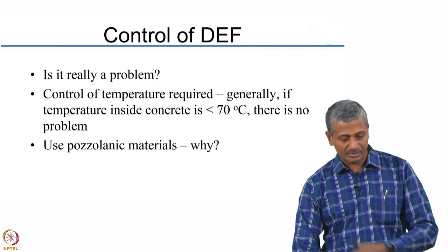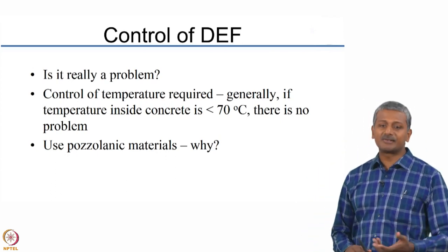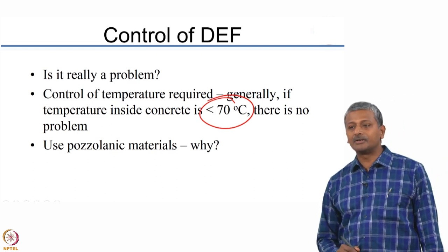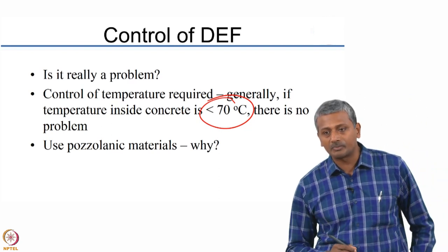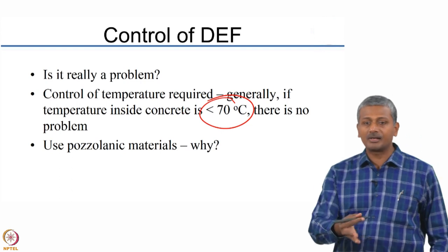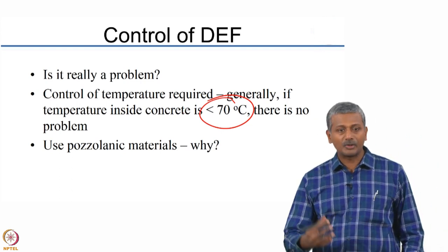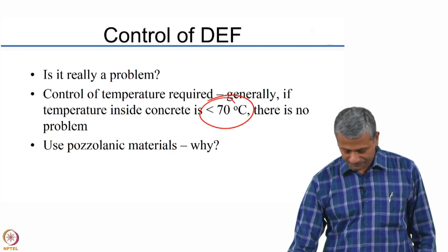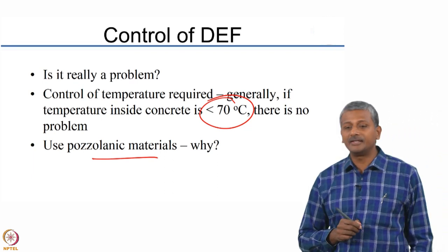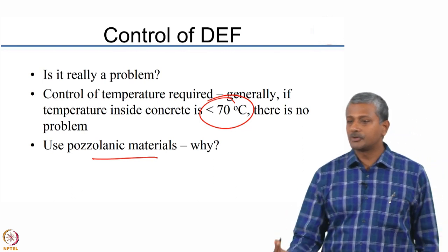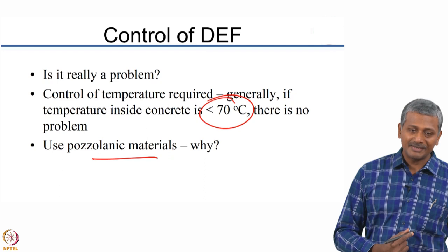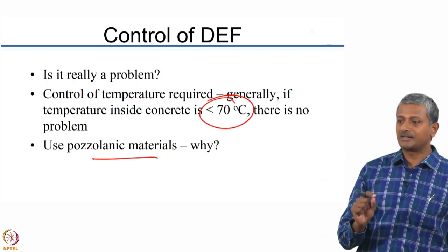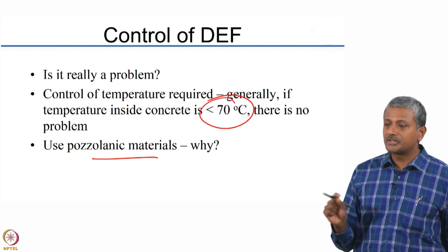A microscopic image from a mortar subjected to delayed ettringite formation shows massive ettringite deposition all around the aggregate and in the ITZ. This is already a late stage — ettringite formation has already led to massive cracking and the cracks are now deposited with ettringite. However, the formation of ettringite around this rim is not the reason for the cracking; the reason is formation of microcrystalline ettringite inside the CSH, which imbibes moisture and increases in size, leading to cracking, after which there is sufficient space for ettringite to grow and recrystallize. The general understanding is now clear: microcrystalline ettringite is what leads to expansive characteristics in concrete, whether in internal or external sulphate attack. Pozzolanic materials can be beneficial in DEF by controlling permeability and because ettringite formation in a pozzolanic system may not be as expansive due to pH differences.